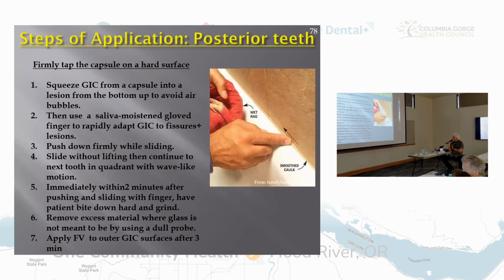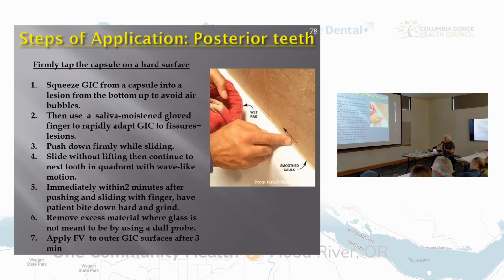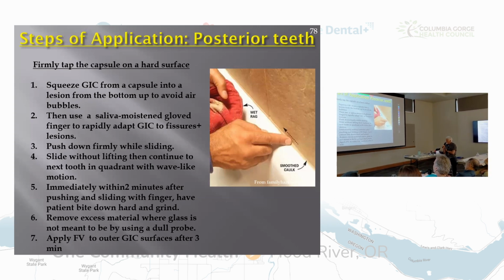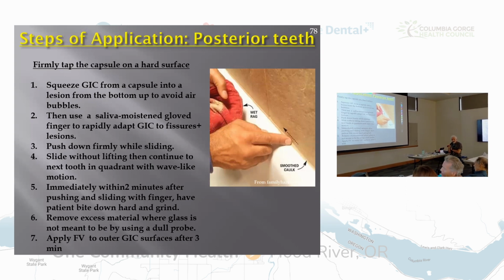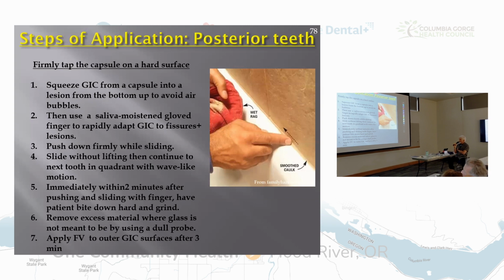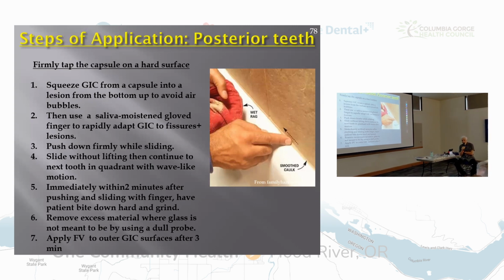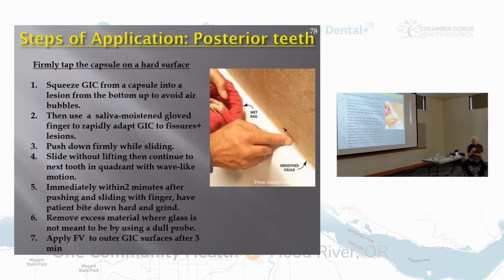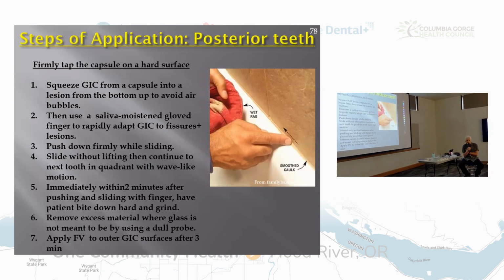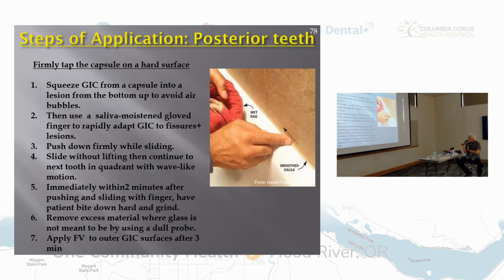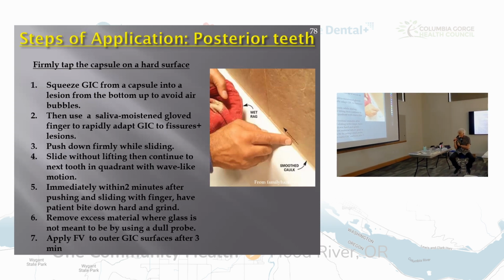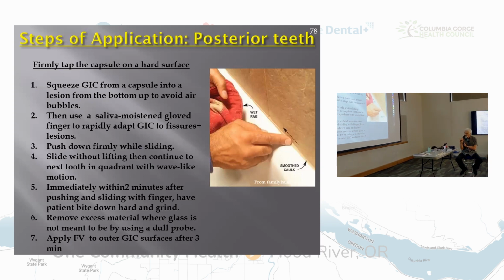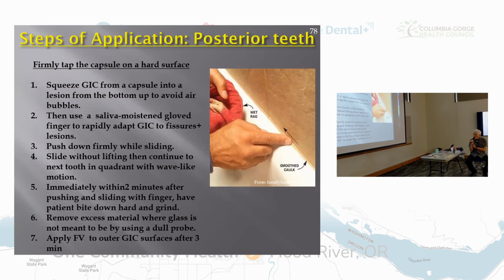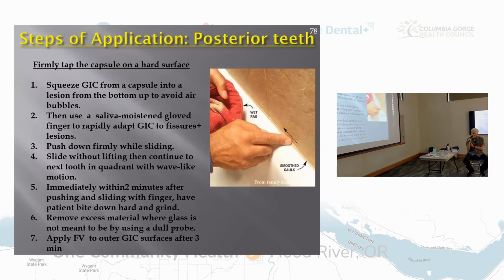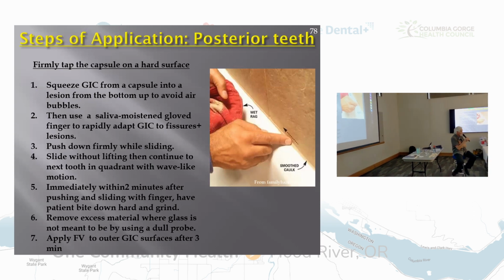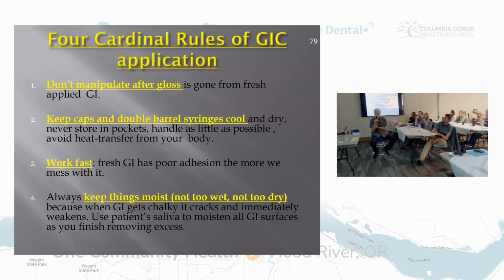Immediately, within 2 minutes after pushing and sliding the finger, have the patient bite down. Within that first 2 minutes, establish occlusion. It's a saliva mouth. You're not going to glue any teeth together. Okay? There's saliva in that mouth. Don't try this on a dry-mouth patient, as Sarah brought up. You might not want to do this because it could stick. But on a normal patient, then you remove the excess material where the glass is not meant to be by using a dull probe. You don't need anything sharp for this. And then you apply fluoride varnish to the outer glass ionomer surfaces after 3 minutes and say goodbye. It's that fast.